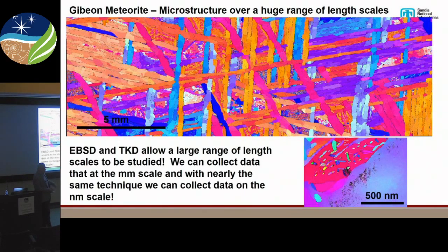We can also do a new technique called transmission Kikuchi diffraction, where we make a thin sample using a FIB or any of the other techniques used for TEM. And you can see here, this is taken at 5 nanometer step size. So this little area here was one of these little areas. And you can see all these nice little austenite, sorry, that would be taenite, I guess, to you geologists, right? It's the FCC phase inside the kamacite matrix, which is the BCC or ferrite to us metallurgists.